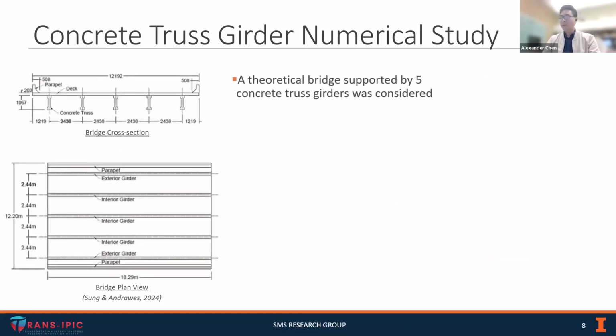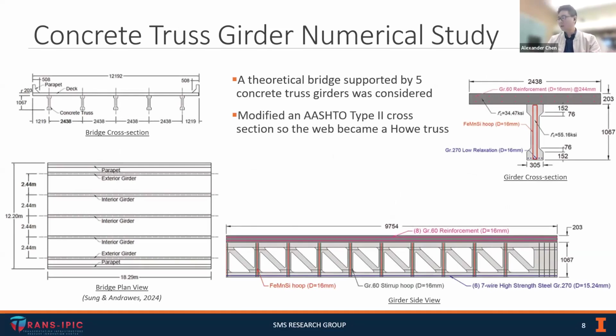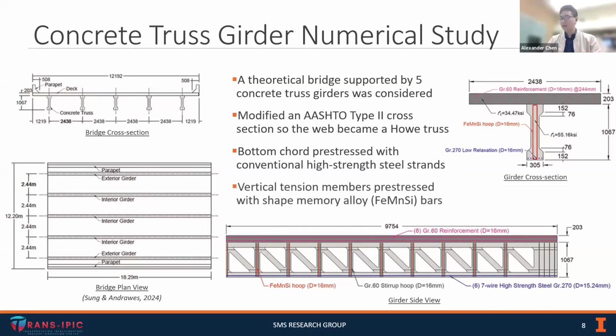So the first step our research group took in exploring this concept was a numerical study, and this was done by a former student of Professor Andrawes, whose name was Min-Soo Sun. He analyzed a bridge supported by 5 of these concrete truss girders. The girder geometry was designed by taking an AASHTO Type 2 cross-section and converting the web into a truss. The pre-stressing methodology is similar to what I described earlier, where the bottom chord uses conventional high-strength steel strands, and the verticals use the shape memory alloys for pre-stressing.